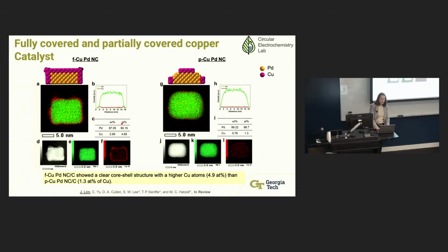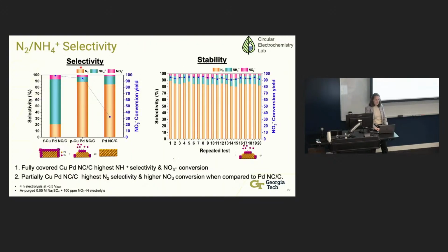And so this showed that we were able to look at fully covered nanocrystals, and then partially covered, where we basically stopped during the deposition. Again, this is what we believe we're seeing. There's still copper all along the edges, but it seems like the corners are rounding out and there's a lot less copper there. We also did ICP-MS to quantify the amount of copper and palladium for these different catalysts. So we looked at these two different catalysts.